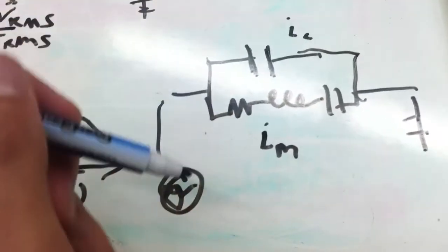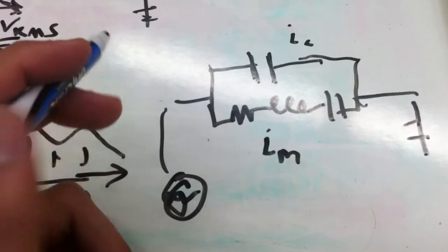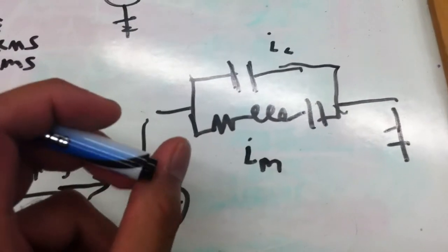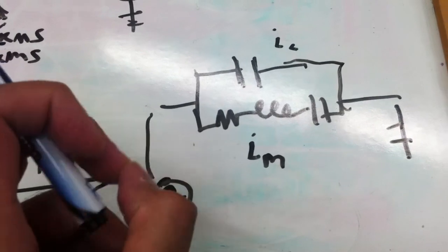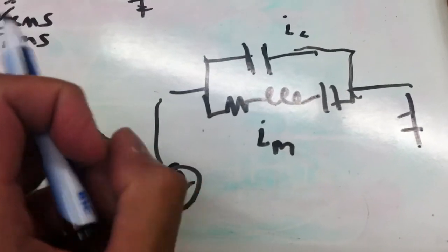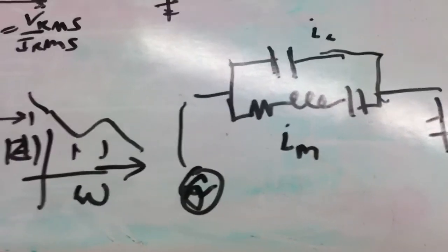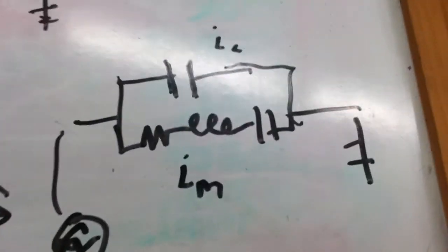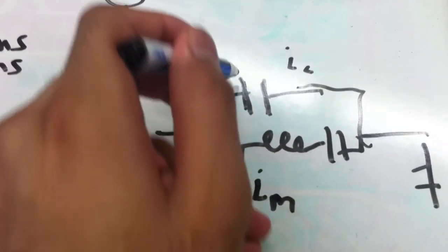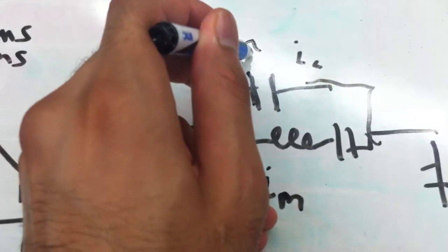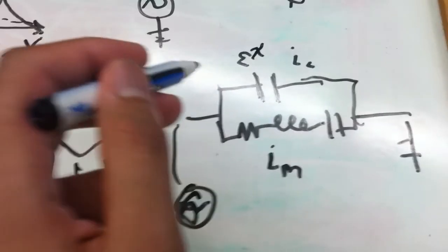That is, if you are clamping a piezoelectric material, it cannot store elastic energy by expanding, and it cannot undergo strain, and therefore the permittivity, or we could say the energy stored when applying an electric field over this material, is less, and thus it's only going to be this. So this material property is related to the permittivity under constant strain, and strain is denoted as little x.